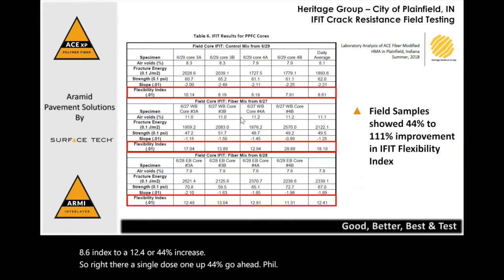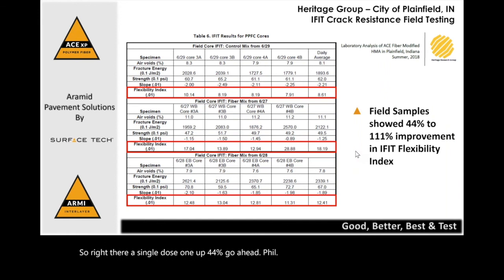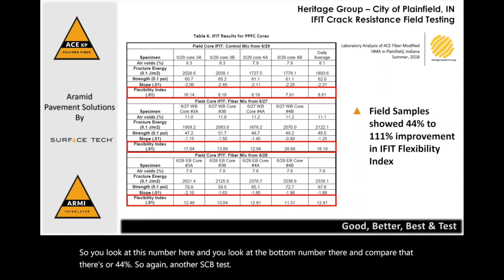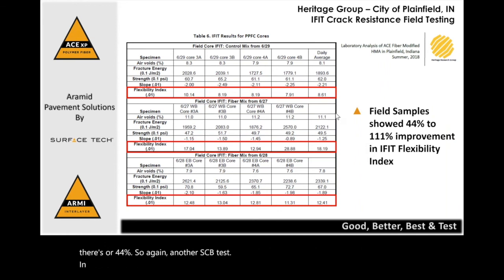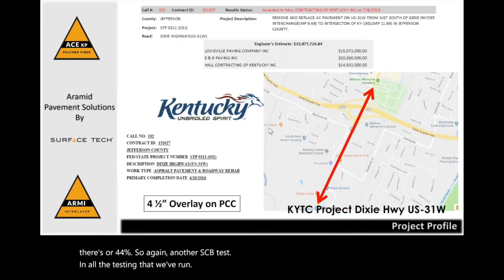Joe, while we don't like to look at that middle box, it is real. I mean, we do hit air voids like that in the field. But the other thing, while we get all excited over the flexibility index, keep in mind these are indirect tests. And so you do see improved results with high air voids. That's not the reality. So the one fallacy on these tests is that high air voids give you better results. That's the exact opposite of what happens in the field. So that's why we're just saying don't pay attention to that one. So you look at this number here and you look at the bottom number there and compare that, there's your 44%. So again, another SCB test, in all the testing that we've run, in that 30-50% improvement range.